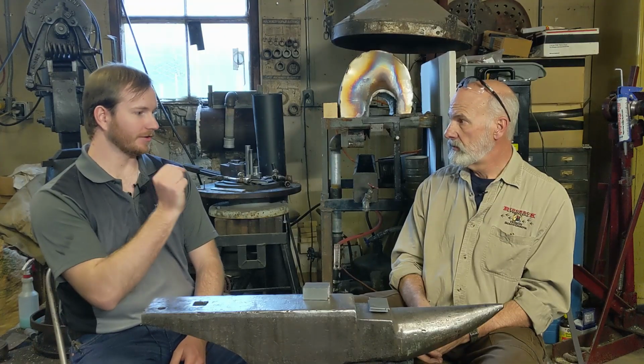And one thing to take into account is that because you are actually etching the steel, you can feel the differences in the layers of the steel. You'll run your fingernail across, and one of my defining factors is if you don't etch deep enough, that pattern will eventually wear down through use. So you want to etch deep enough to where you can feel with your fingernail a little bit of chatter as it goes down the blade.